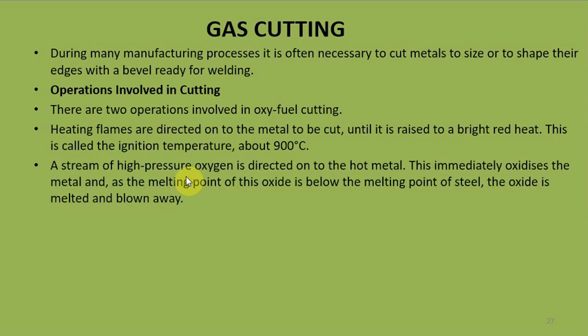A stream of high pressure oxygen is then directed. Once it has reached that bright red color, a stream of oxygen is directed to the hot metal. Why do we need this stream of oxygen? This immediately oxidizes the metal which is in that red zone, and the melting point of this oxide is below the melting point of steel. The oxide is melted and blown away. At 900 degrees Celsius, the oxide will get melted very fast, so we will get a cut there.